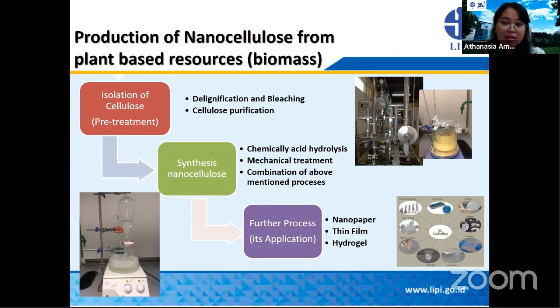We also do have, as you can see in this slide, the bench scale with a capacity of about 500 grams of the biomass. After the delignification, we do the bleaching process. Once we get the highly purified cellulose, we can synthesize it into nanocellulose. The main process that we adopt is chemical acid hydrolysis as well as mechanical treatment. We can also do a combination of the above-mentioned processes. Once we get the nanocellulose, we can further process it for various applications.